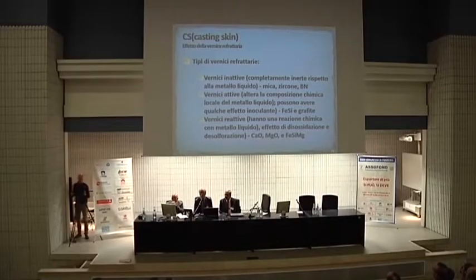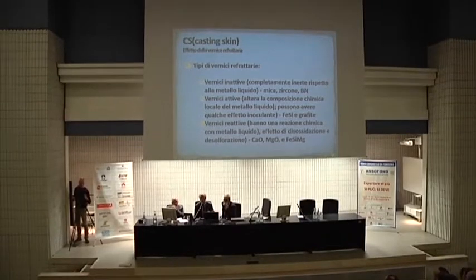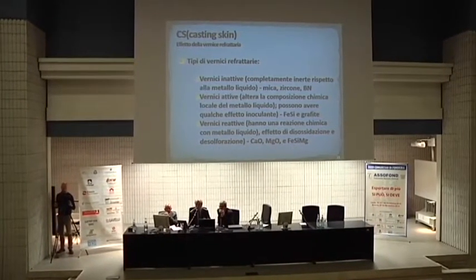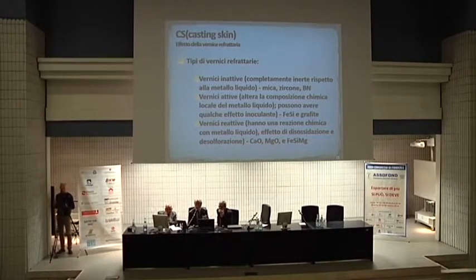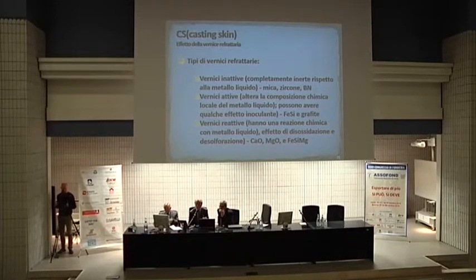And so, some of the experiments were, I already told you that you can decrease the effect of casting skin by shot blasting, but in the regions where you have pores, of course you cannot shot blast, so you have to address the problem in a different way, and that different way is to use mold coatings, and we classify them as inactive, active, and reactive. Okay, inactive means there is absolutely no reaction, there is just a barrier. Active, they will alter the composition of the metal in the layer, and reactive, they have a reaction, like when you add magnesium, then you have reaction with the metal. And I'll give you some examples.